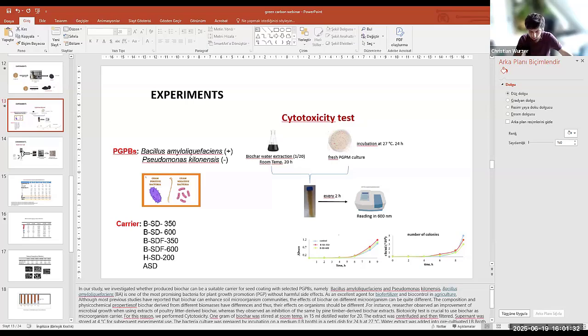So I have another question. You checked the hydrochar after leaching, yes. Did you also check the low temperature wood biochar after leaching? But as I said before, the dry carbonization leaves the volatiles in the organic materials, hydrophobic materials not dissolved in water. Because of this, we cannot wash. But in case of hydrochar, the hydrochar is obtained in aqueous phase, so the remains on the hydrochar can be water soluble. Okay, so you didn't see any difference when you washed the dry biochar. Yes.